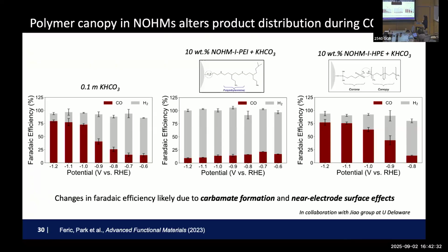But if you have ether groups, it's a weak enough binding energy, you can start to convert quite a bit of CO2 to CO. So the way you can convert carbamate into CO, you actually have to run your electrochemical cell at 60 degrees or higher. Then you start to thermally regenerate your material, release that CO2 locally, and you can start to convert that CO2. So we start looking at the Faraday efficiency. If you're not familiar with electrochemical reactions, this Faraday efficiency is basically telling you the selectivity towards a certain product. So if you compare here versus here, it's not exactly the same.